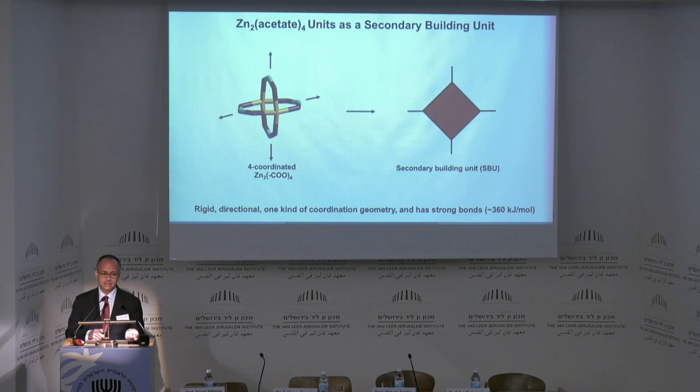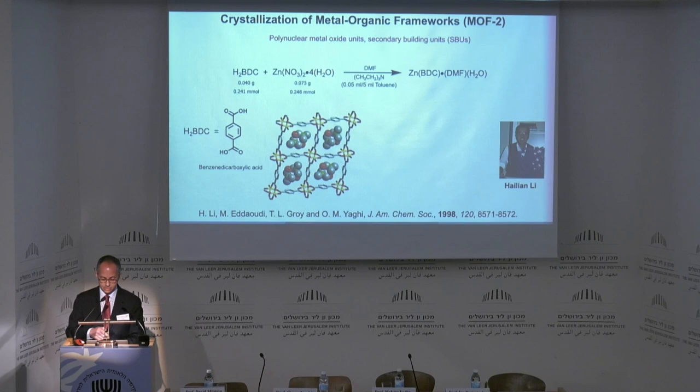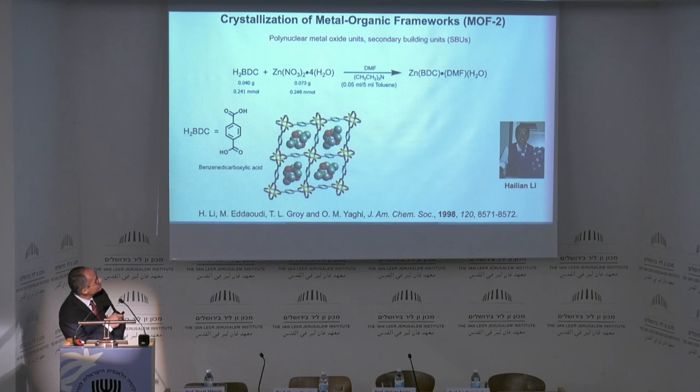That was really the key insight into changing that equation around, where instead of having those nice structures, now they will be nice, but also, as you will see shortly, porous. Now, a development that I don't talk too much about is that we found the conditions under which to crystallize things from strong bonds. So clusters like this can now be linked by this terephthalate to make two-dimensional structures, and DMF fills the pores as a solvent that is trapped during the synthesis.